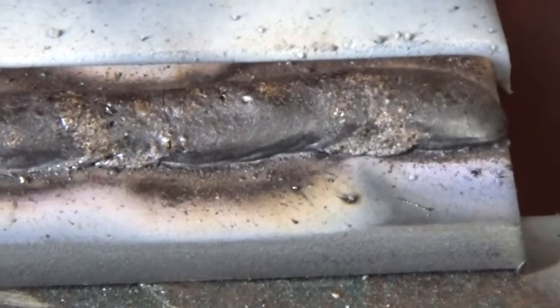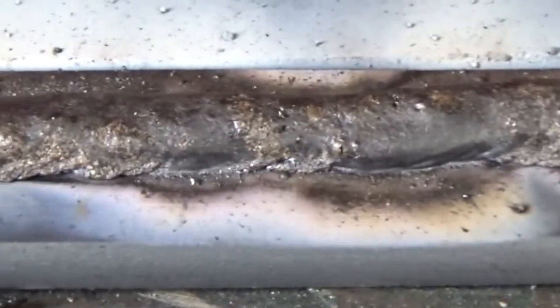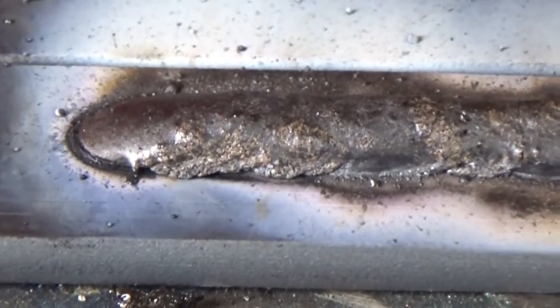So the first weld: rutile electrode, negative, welding current 65 amperes. It can be clearly seen that the puddle is quite cold. Metal spreads poorly on the details. The welding process is too slow. The arc burns dimly. It is unstable, i.e. it walks from side to side, so it affects the seam. Let's clean the weld and look at that.